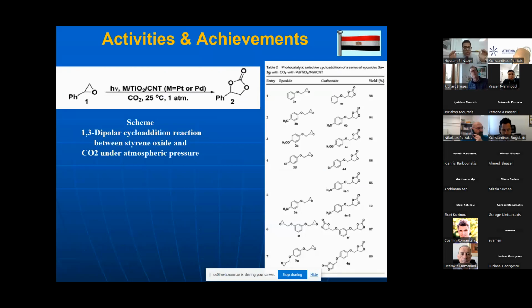Also, we applied this photocatalyst in a reaction of transformation of styrene oxide to valuable cyclic carbonate derivatives. Also, we introduce the carbon dioxide to styrene oxide to produce carbonate. So we have two targets.